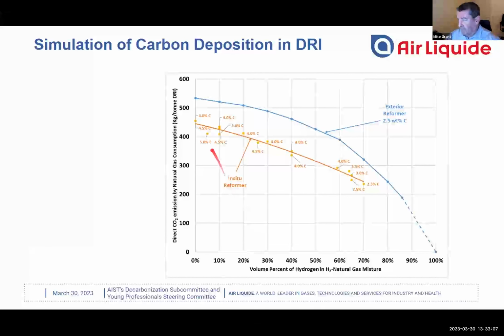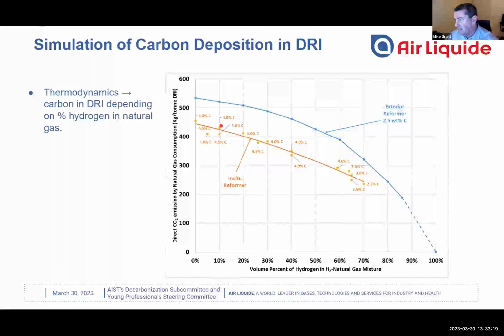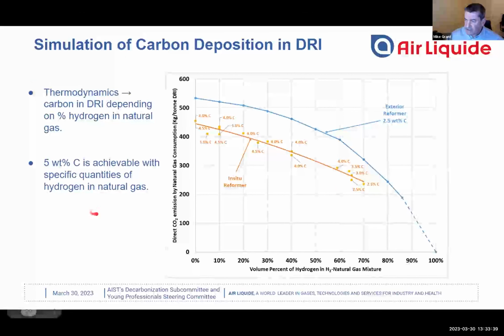Now, I did a little thermodynamic simulation of carbon deposition in the pellets during DRI making. And you can see that we can put carbon in the DRI even if we start adding hydrogen in the mixture with the natural gas. And theoretically, at least, and it's been published also, you can get up to 5% carbon in the DRI, which is good. That's chemical energy we can use in the steelmaking process. And so this is quite achievable, thermodynamically at least, and evidently practically. And so we can make a hot metal if we want to.